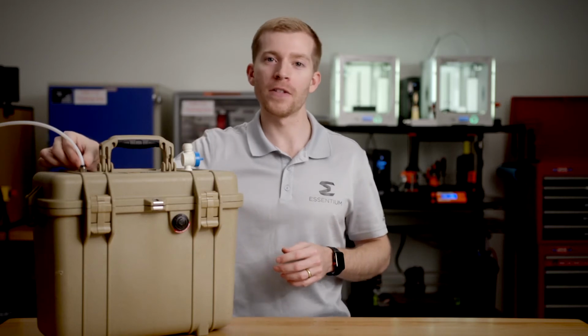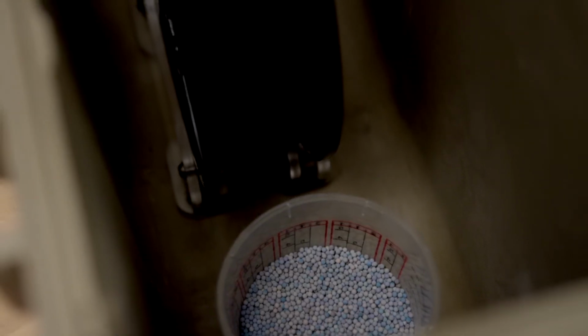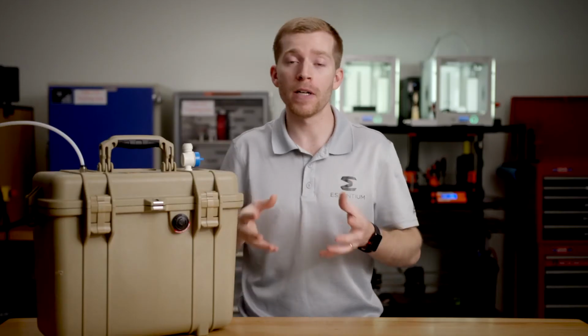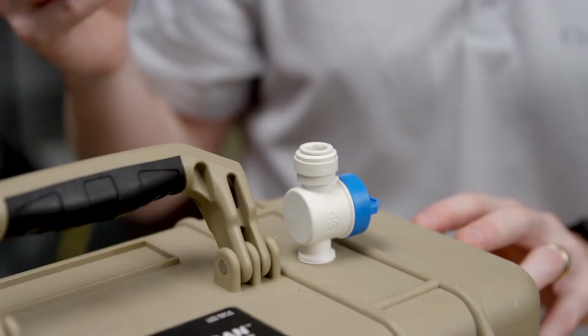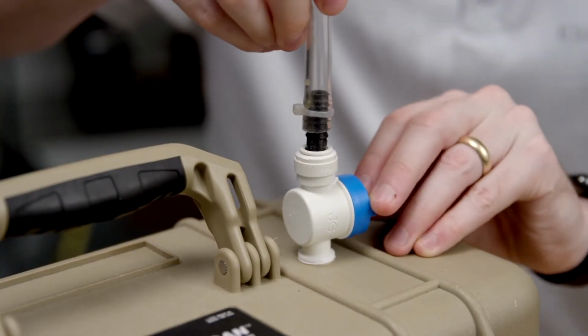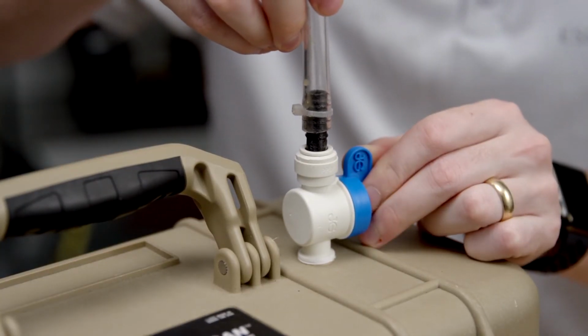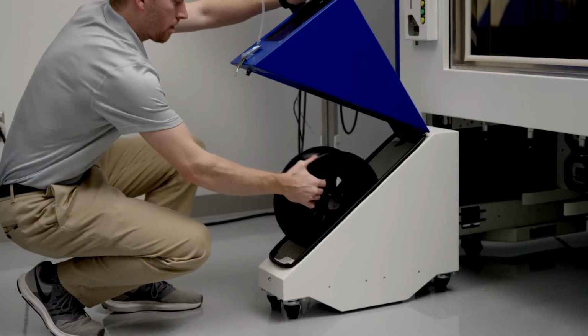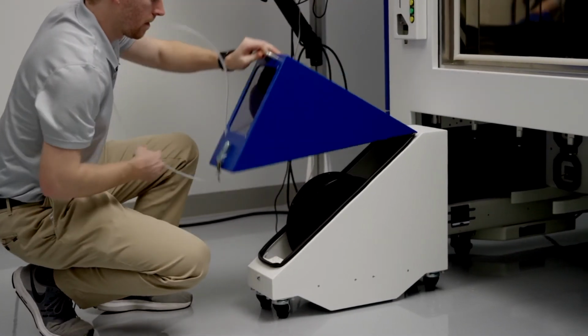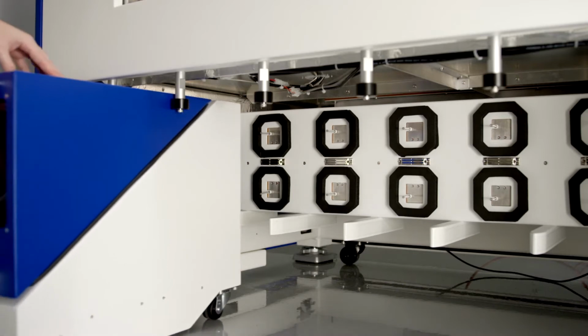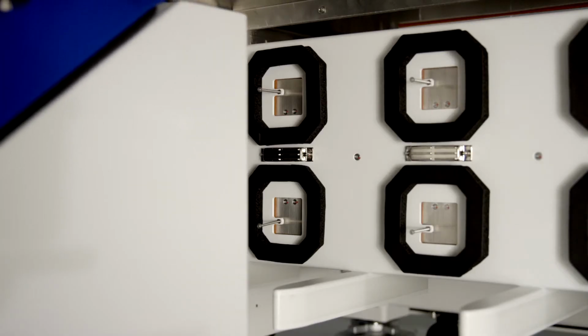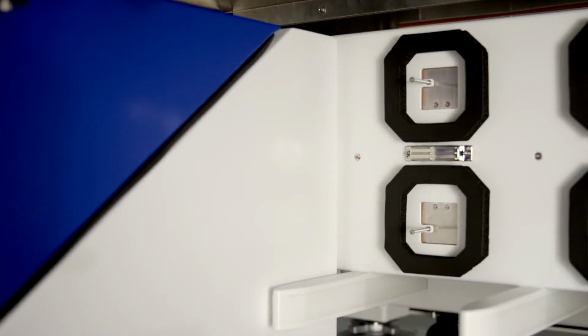A very economical solution for a dry box can be made by modifying a Pelican case with a push fit connector and a Bowden tube, adding a pouch of desiccant and some roller wheels for the spool to sit on. For very moisture sensitive materials like nylon and TPU, we recommend adding a push fit valve that allows you to purge the container with nitrogen purchased from a welding supply store. The Essentium HSE printer addresses this need by having airtight filament carts which plug into a desiccant drying manifold in the front of the machine.